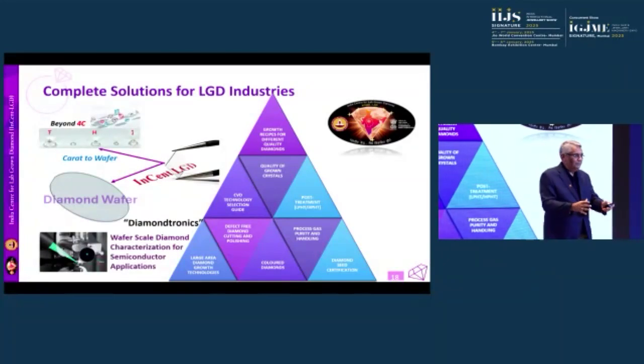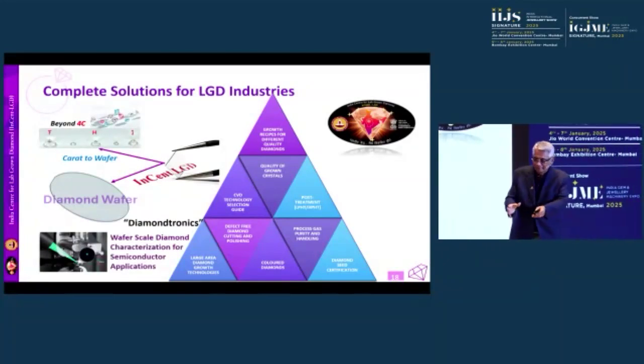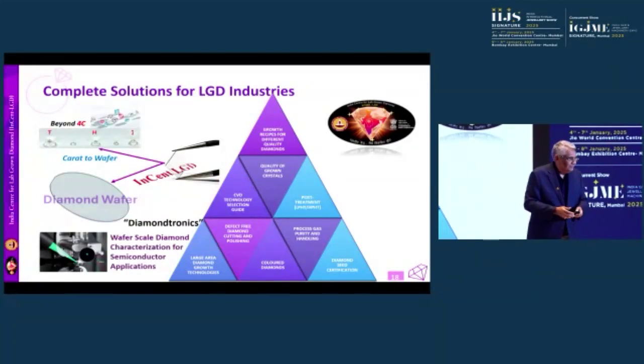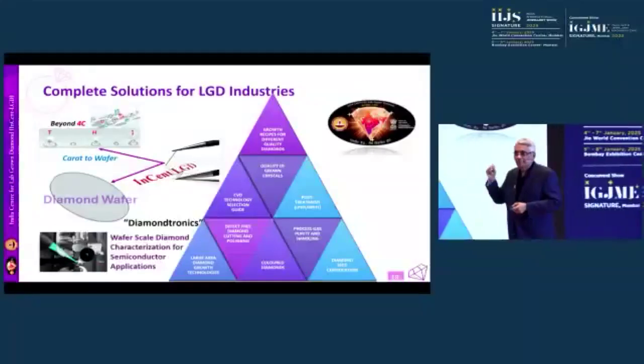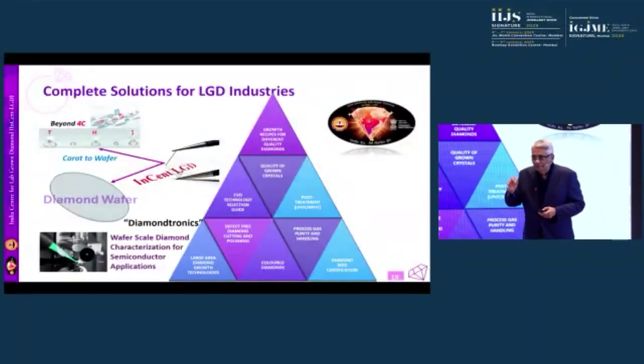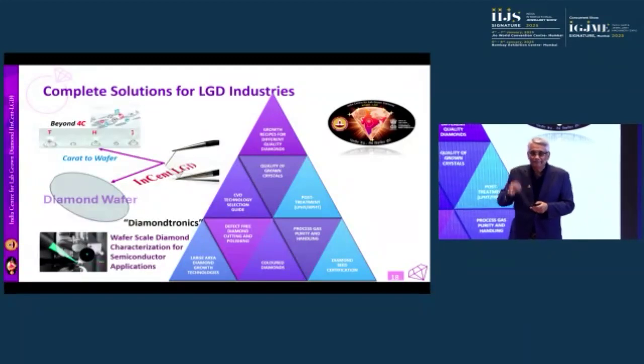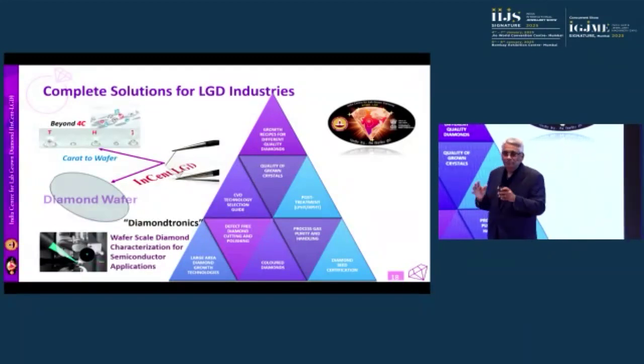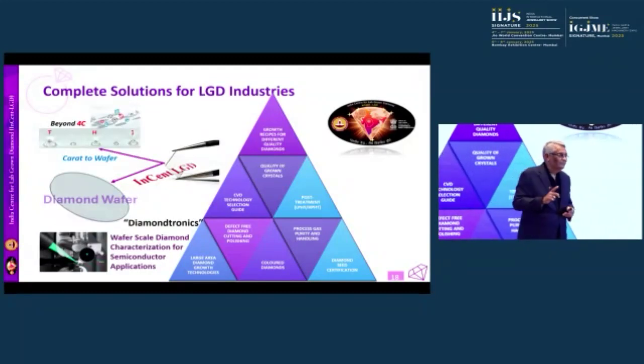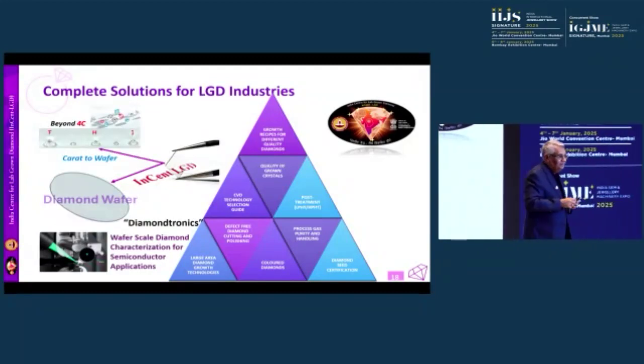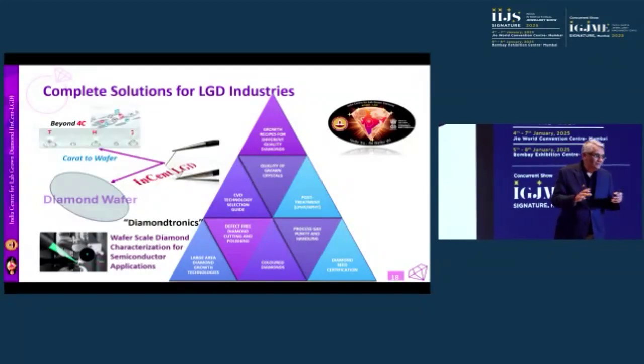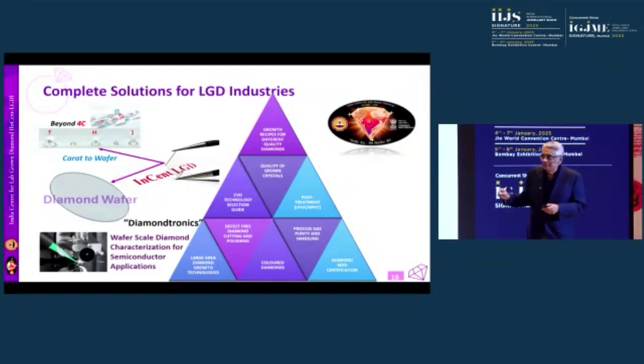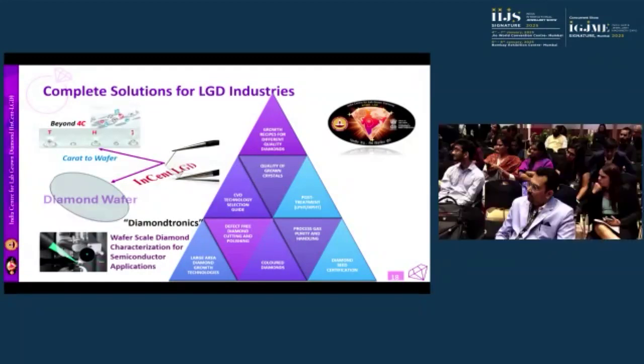So let's say I take a piece of diamond, put it under high energy gamma rays or an electron source or X-rays, right? I create defects and those defects will make the diamond colored. But then you need to control the radiation damage in such a way that you do not lose the basic diamond structure, right? This is very important. So we have tested some of the colored crystals, and to our surprise, there is no diamond structure there. That means whatever has been done, it is done to the extent that the diamond structure is completely lost. This is where you need our help, scientists' help, right?